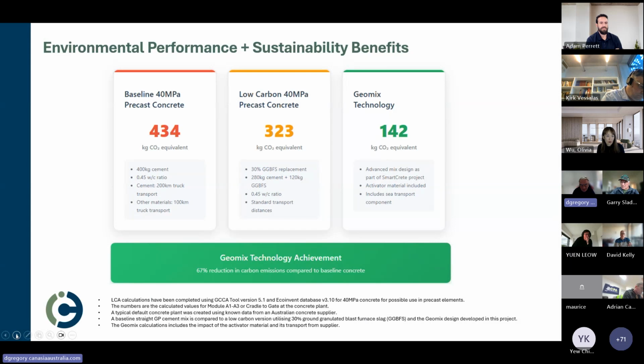Okay, here are some of the figures for production of CO2 per meter cubed. And I've taken this from some work done by Jason Chandler, who is very important in our development activities in this field. Obviously these figures vary for the particular site, particular geographical location, but this just gives you a general feel for the reductions which we can achieve in the CO2 emissions. For a sole cement-based system, you're around this 434 mark, kilos of CO2 for a 40 MPa system. When you substitute some of the cement with slag, this drops to around 323. And with our system, we're at the 142 mark.